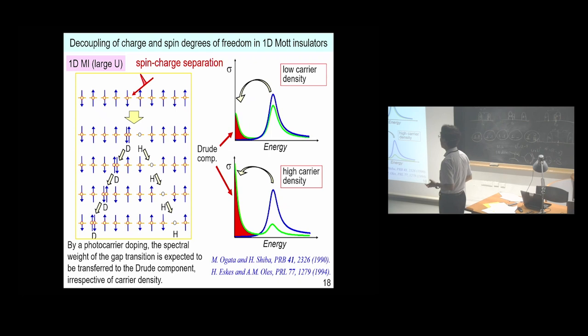In the case of the 1D Mott insulator with large U, the carrier dynamics is considerably changed. For example, by a photoexcitation, a doublon-holon pair is generated, which moves without disturbing the anti-ferromagnetic spin background. So, the charge dynamics is decoupled from the spin dynamics, and the carrier can freely move. This feature is called spin charge separation. So, by a photocarrier doping, the spectral weight of the gap transition is expected to be transferred to the Drude component, irrespective of carrier density.